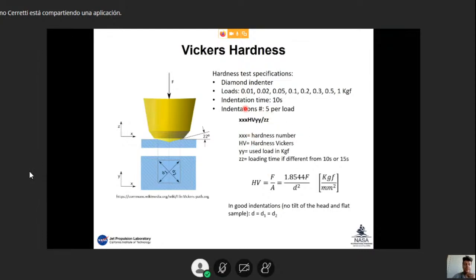The number of the Vickers hardness is generally reported like this. We put first the hardness number, the value that we obtain here with this equation. Then HV stands for hardness Vickers, so we know that it has been done with the Vickers. The difference between the Vickers and the Brinell is the shape of the indenter. In the Vickers, it's a square base pyramid. Instead, in the Brinell it's a sphere. Then we put the used load in kilograms force and the loading time. This value is reported only if it's different from 10 to 15 seconds.